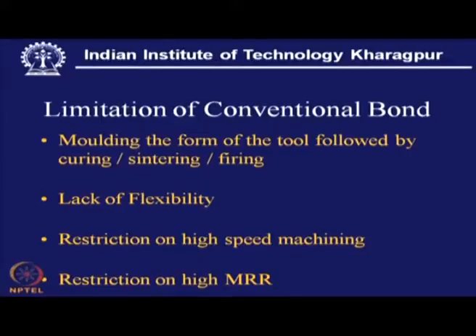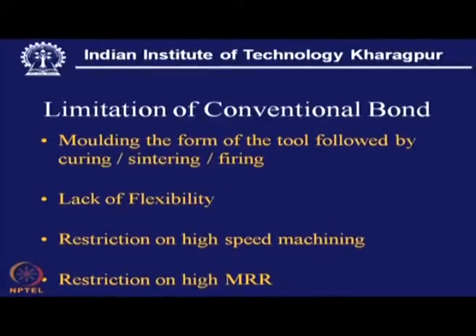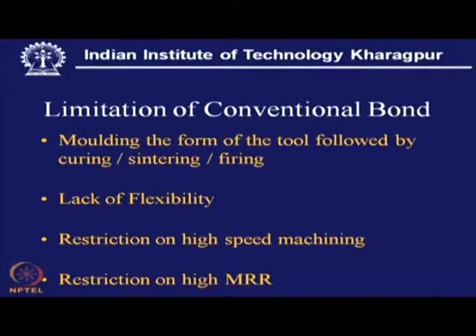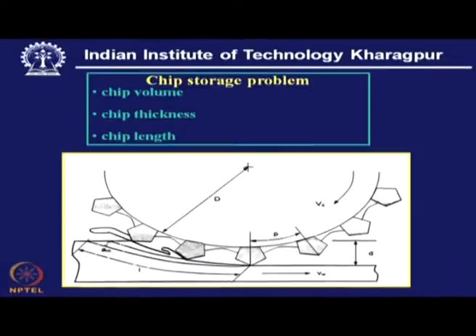Now, this particular bond also has a limit, particularly for high speed grinding. This is true in particular for vitreous bond, where the material is brittle in nature, and because of the high speed there is a risk of bursting of the bond, and there is a restriction on the speed. Then we also find restriction on high material removal rate, and this can be understood if we look at this figure.